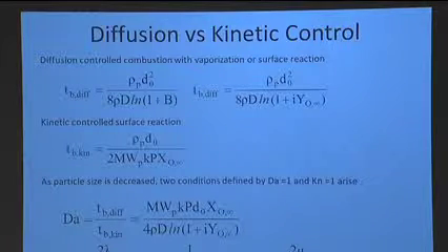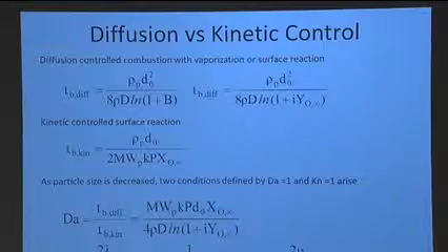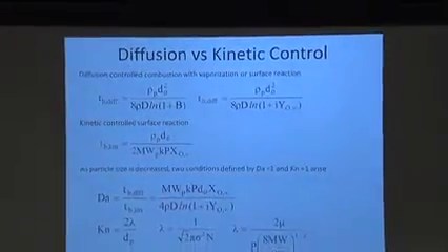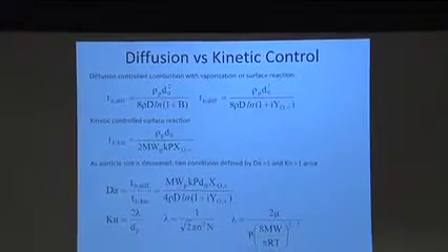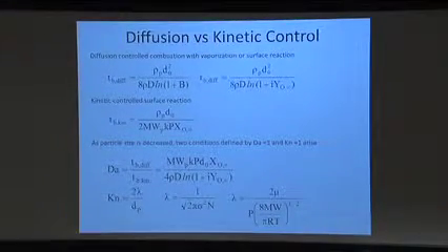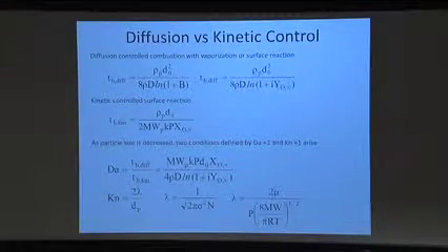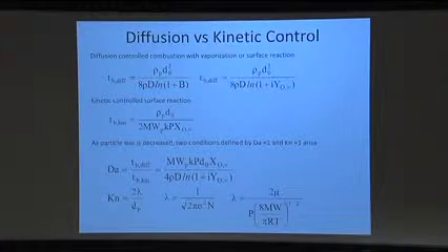And what I find then is that burning time, if I have that diffusion controlled situation, will scale with what's on the right-hand side here. And this is the case where I have that envelope flame around the outside. So you can see it's proportional to the original diameter of the particle squared. The density of the particle, rho d here, is essentially the density of the gas, the diffusivity in the surrounding gas. And B here is the mass transfer or Spalding number, and essentially the driving force for the system.